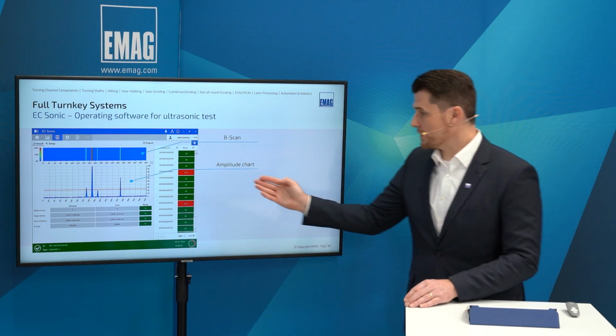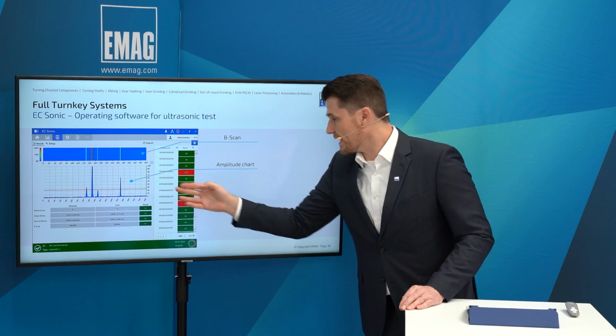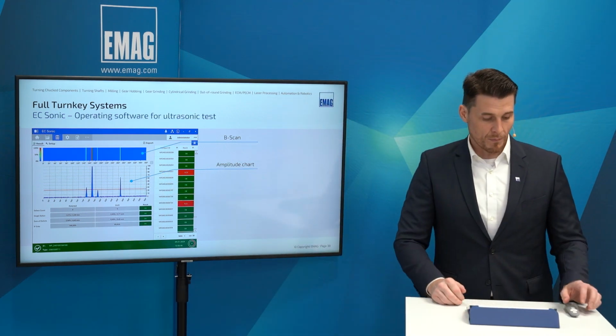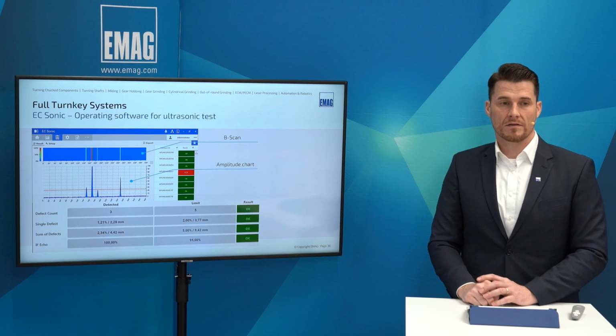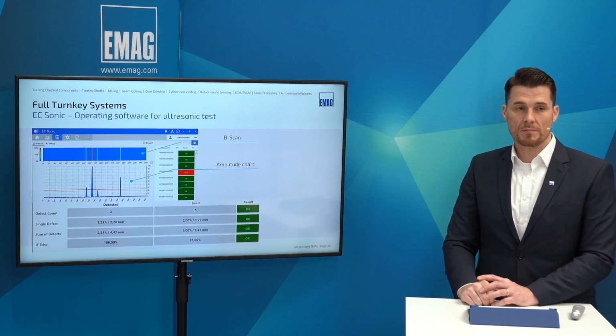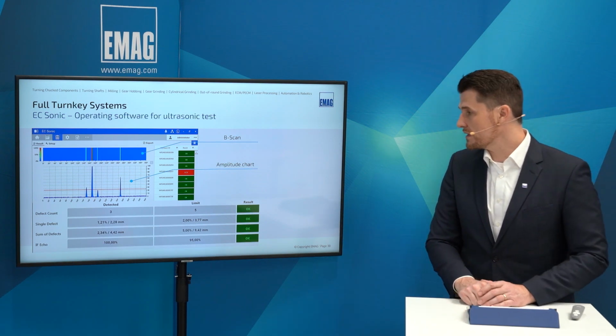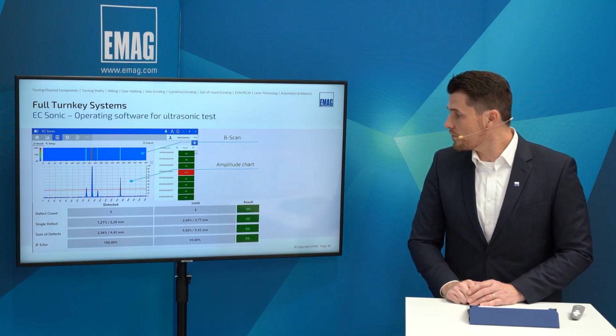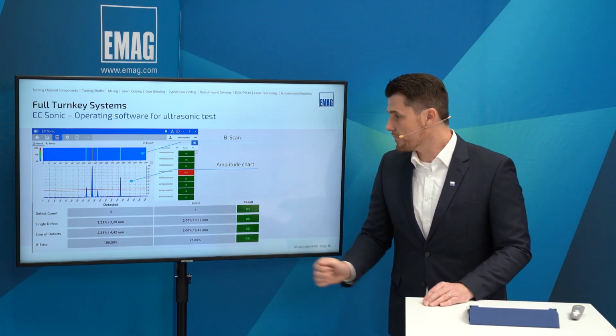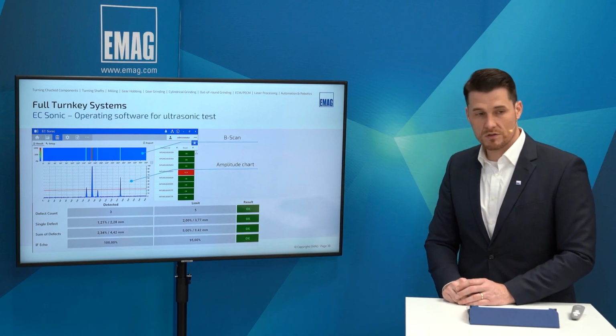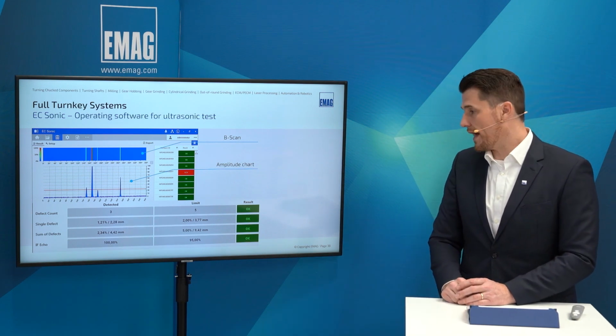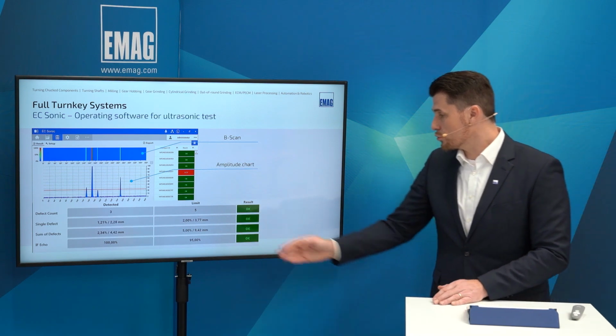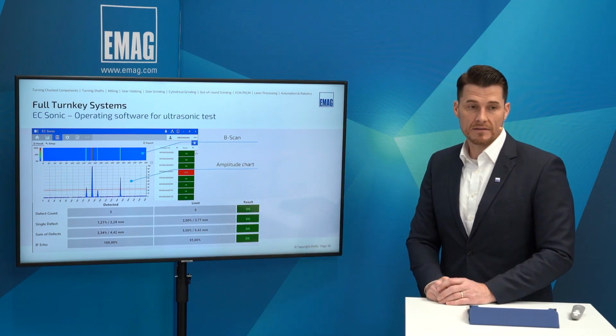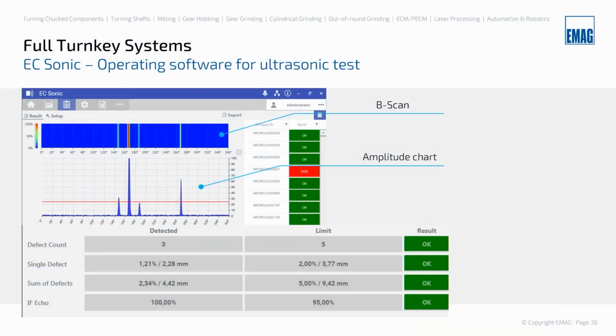And here you see in the amplitude chart, you also see the red line, the gate, and the peaks that are above it. And again, to view here a bit better on this chart, which we have chosen, 3 defects were over the red line. The limit is 5. The biggest single defect was 1.2 millimeters, 1.2%. 2% are allowed, and the sum of all detected defects is 2.3, and 5 is allowed. So 3 times okay result.